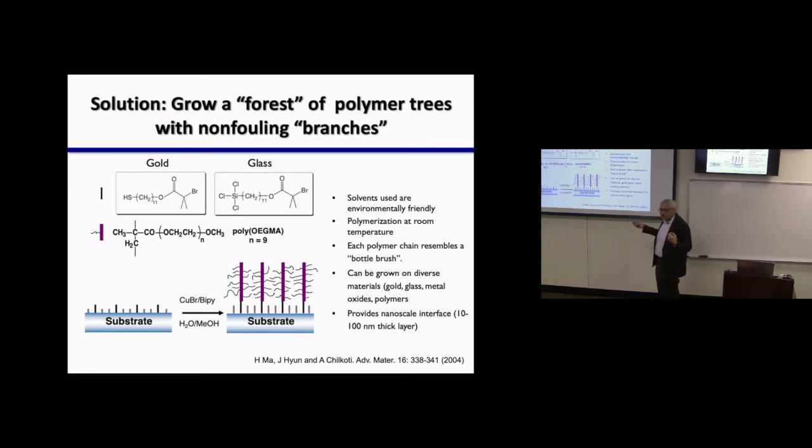And if you select the right monomer, the right building block, you will end up with this tree-like architecture, where the backbone is not PEG. The backbone is actually alkane, it's greasy, but the branches are short polyethylene glycol. So think of them as branches where the leaves are short PEG chains. This is a different architecture from linear PEG because the PEG is distributed as short branches.